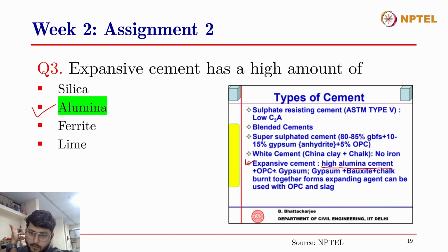I have taken this picture from the NPTEL lecture course, and you can see here that expansive cement has a high alumina content. It is generally made by burning gypsum, bauxite and chalk. These minerals are burnt together in order to produce the expanding agent. Now, bauxite is the aluminum ore, and that contributes to the high alumina content in this expansive cement.